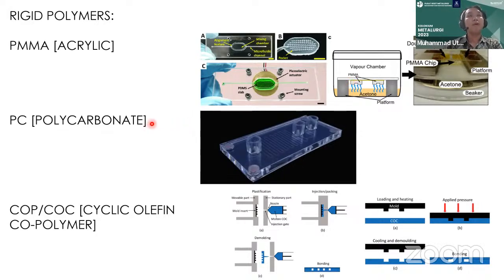We also have polycarbonates and COP or COC, the cyclic olefin copolymer. So a lot of commercial microfluidic products use this kind of rigid polymers as their materials, and the way industry mass produces this kind of device is usually using injection molding or the hot embossing process. So we can get the mold either using micromilling or soft photolithography, and then we can do this mass production using something as simple as injection molding or hot embossing.